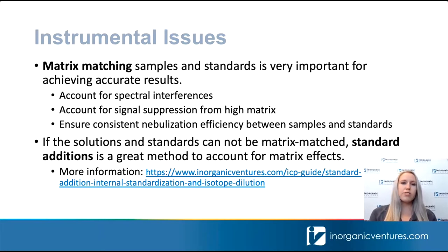So if you are not able to matrix match your standards and samples, we recommend performing a standard additions method where you spike the standard directly into your samples, and then you compare the results of the sample ran on its own and the results of the sample with the spike added. So I've added a link at the bottom of this slide to our website that goes into a little bit more detail about how to perform standard additions method and gives some examples there. This method is a bit more time consuming than performing your normal calibration. However, it is effective for accounting for these matrix issues.